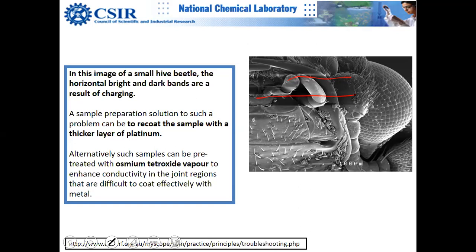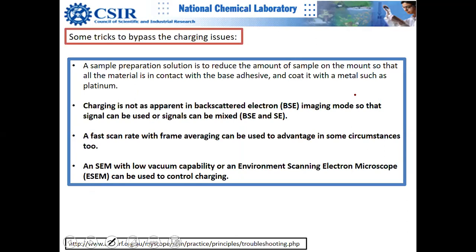Here, one can pre-treat. It's not a coating. Please treat it with osmium tetroxide vapor. So that's one way of doing things. For charging issues, you can always use a fast scan rate, so you reduce the dwell time. Less dwell time is always good.